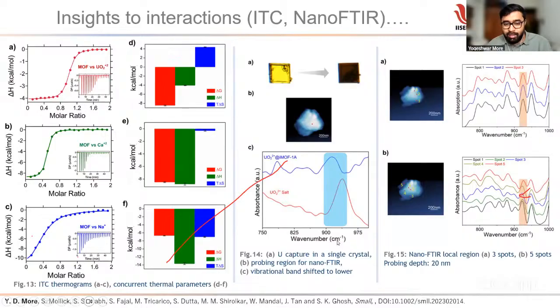We found that when compared to the uranium salt, in the uranium adsorbed MOF, the absorption intensity for the uranyl cation goes nearly 20 centimeter inverse down, which is the reduction of bond order of uranium and oxygen. And since the uranium oxygen bond is weakening, it means the uranium and nitrogen bond within the MOF is strengthening, and thus the stabilization of uranium within the confined structure is forming. That is one of the key tools to understand why this is happening.